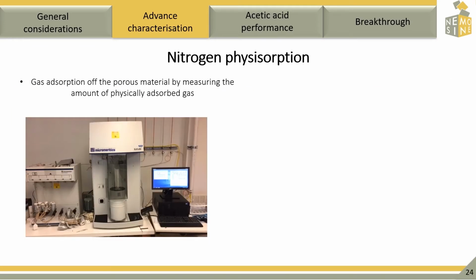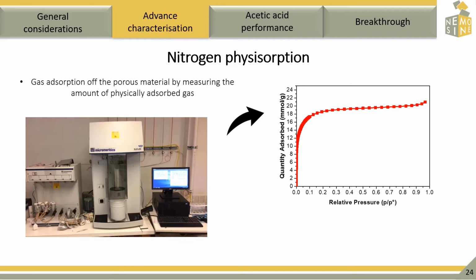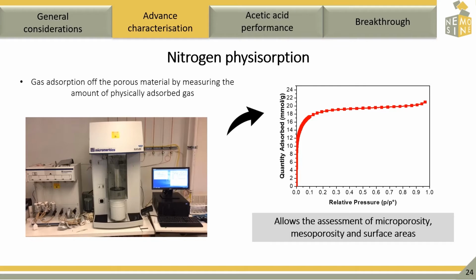Gas adsorption is a well-established tool for the characterization of textural properties of our materials. Nitrogen adsorption is widely used by the MOF community and consists in adsorbing nitrogen into the pores of our material and measuring the amount of physically adsorbed gas, and from this calculating surface areas and volumes. This method is important to obtain information about mesoporosity, microporosity, and surface areas of our samples.